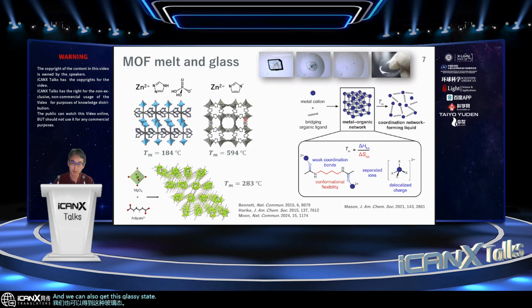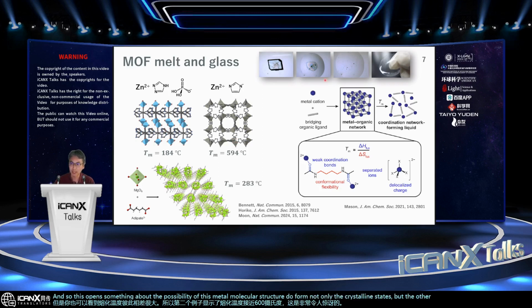The same thing happens for another example made of zinc and the molecule imidazole. But you can also see that the melting temperature is quite different between them. This second example shows a melting temperature close to 600 degrees C, which is very surprising for a molecular structure. This opens up the possibility that metal molecular structures form not only crystalline states, but also a melt state or potentially a glassy state.